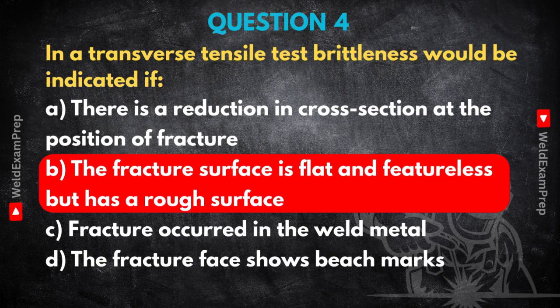Now, if you see that flat, rough break in the real world, alarm bells should ring. Okay. The immediate investigation would be, first, material confirmation. Was the right stuff used? Check the certs, traceability. Then review the welding procedure critically, things like preheat, interpass temperature, any post-weld heat treatment, because those control the microstructure and can prevent or cause brittleness. And you'd also look at service conditions. Was there some unexpected stress or maybe a very low temperature involved?